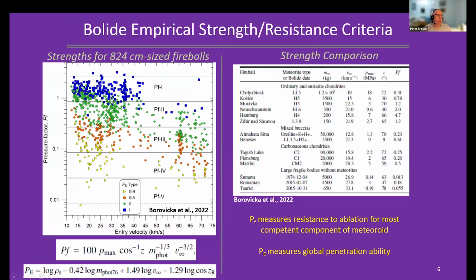All right, so if I look at a series of survey measurements done from ground-based cameras, this was done by the European Fireball Network over the course of 1 year in 2017. If I look at the pressure factor here, so things up here are more resistant, they experience higher pressure, and I plot them as a function of velocity, and I color code by Pf type. So the blue are the strongest material that survives deepest in the atmosphere. The yellow are things that tend to break up higher in the atmosphere. We see overall there is a correlation, that particularly at lower velocities, there's a lot of fairly dense, fairly strong, deeply penetrating material, and there's some, but not as many, weaker material.